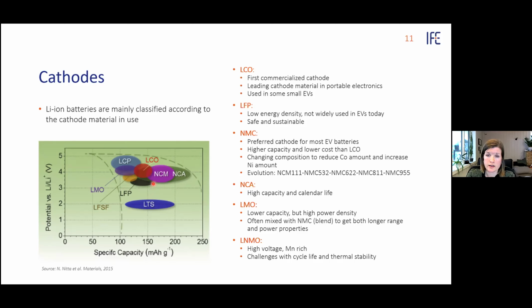NMC, lithium nickel manganese cobalt oxide, that's basically the preferred cathode for most EV batteries. It's here in the graph. It has a very good capacity, also lower cost than the LCO. There's a trend to change the composition of NMC to reduce the cobalt amount and to increase the nickel amount, meaning that NMC has been through a bit of an evolution.